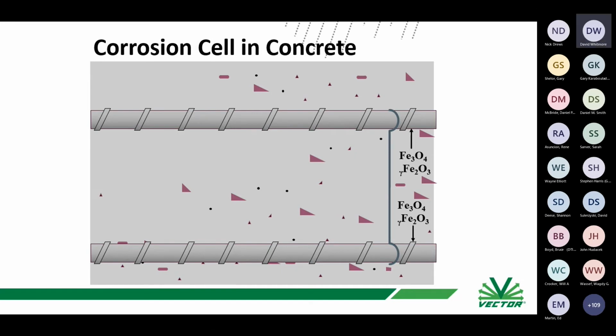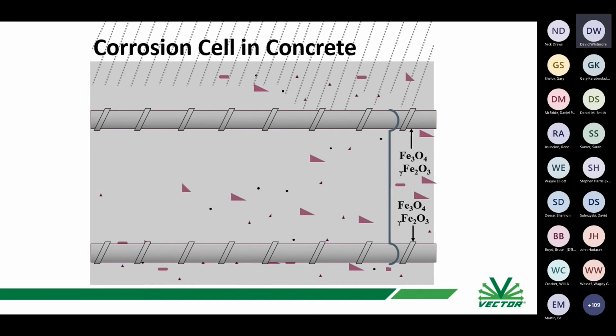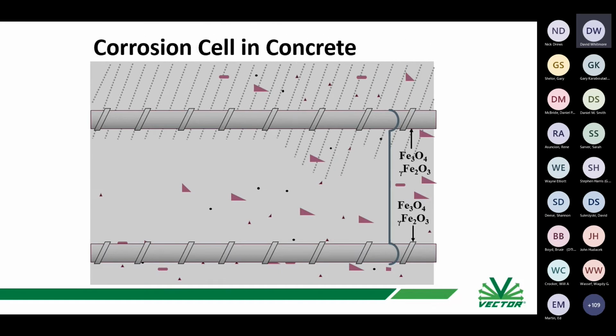But if the concrete becomes contaminated with chlorides or the concrete surface becomes carbonated down to the level of the reinforcing steel, the chemistry of the concrete is no longer compatible with maintaining that passive oxide film. The pH isn't high enough if you've got carbonation, or the level of chlorides exceeds a threshold for corrosion to initiate, at which point this passive film breaks down.